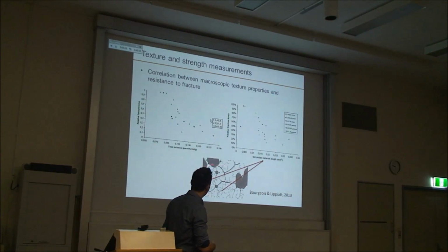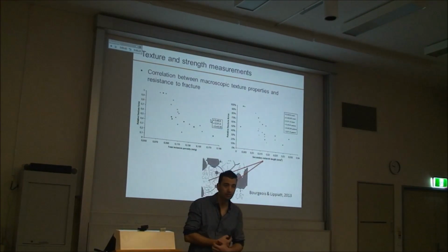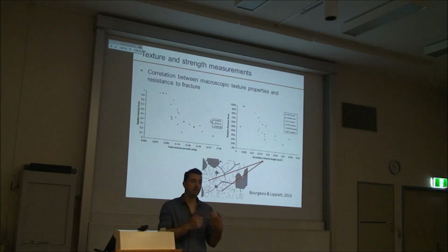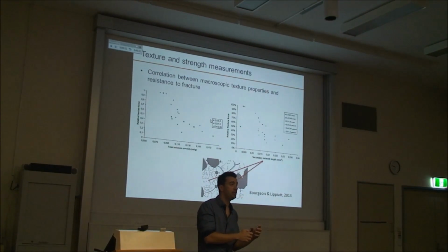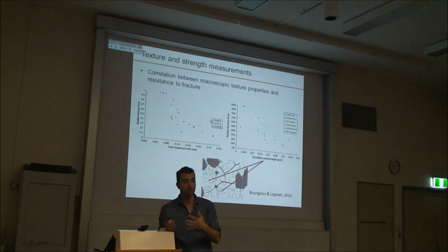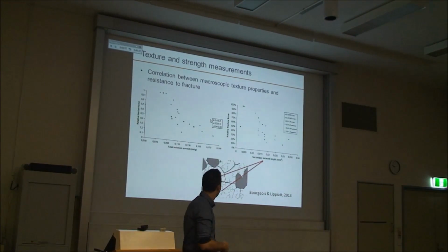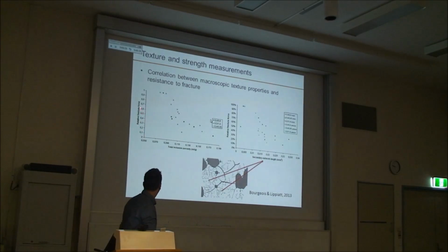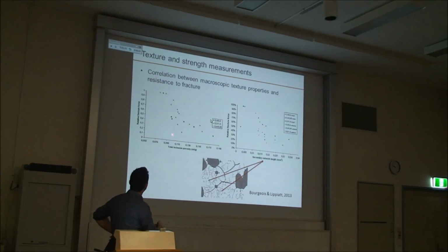So this is a picture of texture of concrete, a 2D slice, the big grey aggregates, and the different fractures within the concrete. So what they were looking at is, is there any macroscopic texture property that is related to the fracture properties we can measure on the impact load cell? And the first graph on the left shows a reduction in the fracture force. So this is the force you need to apply on the concrete to break it.